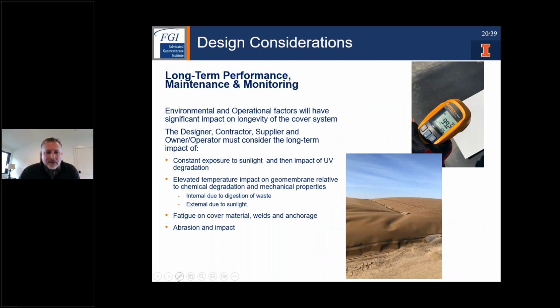Environmental and operational factors can have a significant impact on the longevity of the cover system. So the designer, the contractor, the supplier, and the owner need to consider long-term impact of, first off, constant exposure to sunlight, elevated temperatures, which can be significant on these cover systems, and then also fatigue problems with the welds in particular on these cover systems, because they're moving around a lot. We need to constantly do inspection for small fatigue cracking, things of that nature that might occur, and make sure those get repaired before they become major issues. And then finally, of course, abrasion and impact can also cause small pinholes and other things that need to be repaired before they become a big issue. Next.